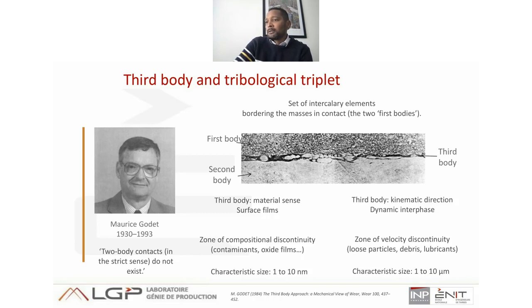In the sense of the materials, there are interfacial films that mark a zone of compositional discontinuity with characteristic dimensions of the order of 1 to 10 nanometers. From a kinetic point of view, it is a dynamic interface where a velocity discontinuity can be observed. From this point of view, the characteristic dimensions are considered to be between 1 and 10 micrometers. This third body can be artificial, in which case it is a lubricant. It can also be natural and induced by the reactivity of the surfaces or the degradation processes of the surfaces.